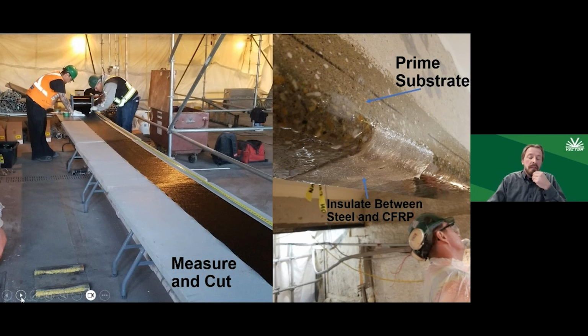We want to set up as close to the installation area as we can, especially if we're dealing with hot or cold temperatures. To expedite the process, we want to saturate and then get that fabric or laminate onto the concrete that's going to be protected, and give the technicians time to work it over and make sure that it's well adhered. One thing of note on the right-hand photo: insulate between steel and CFRP. Anytime there are embedded metals or steel, we have to isolate that from carbon by using glass fiber.